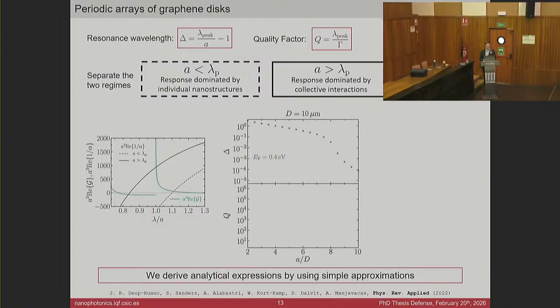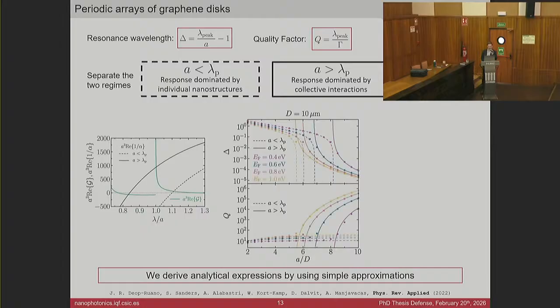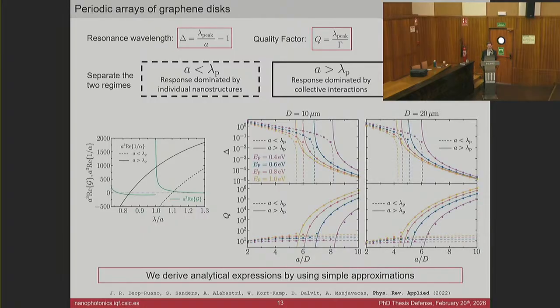and I'm going to show you here how they compare to the numerical results. In one regime, we plot it with this dashed curve. We see that there is a really good match, and also a really good match in the opposite regime. Only in this transition region, it can maybe deviate a bit more. The same for the quality factor, excellent match in both regimes, and we can see how the quality factor, once we are able to sustain a lattice resonance, grows by several orders of magnitude as we increase the period. We also obtain really good match with the rest of the numerical results that I explored.